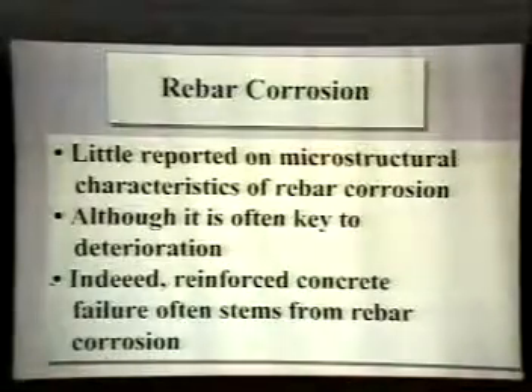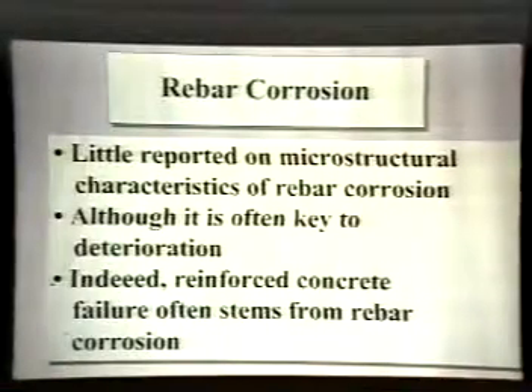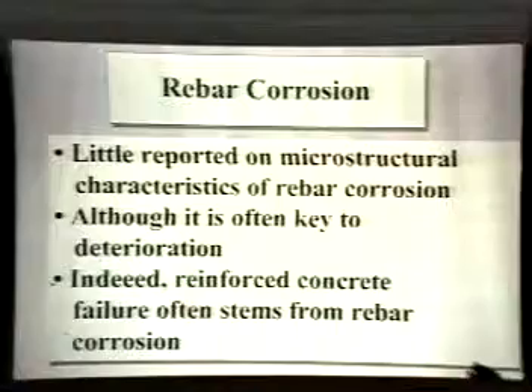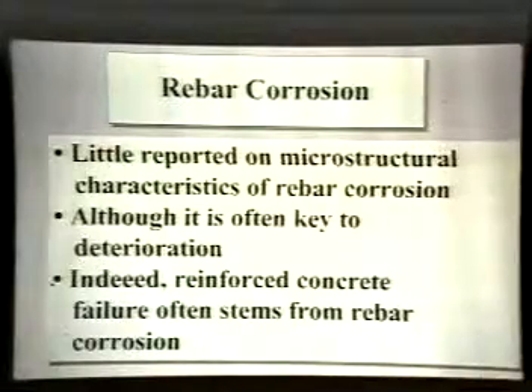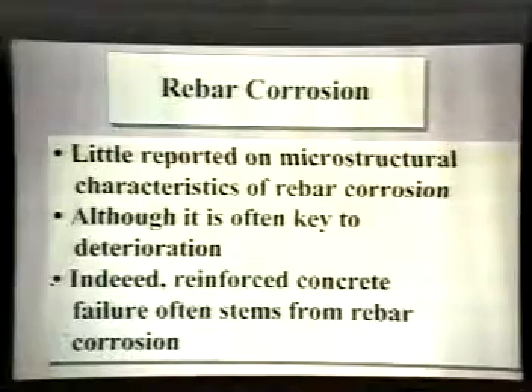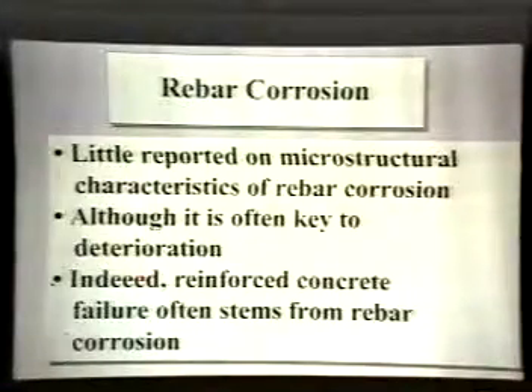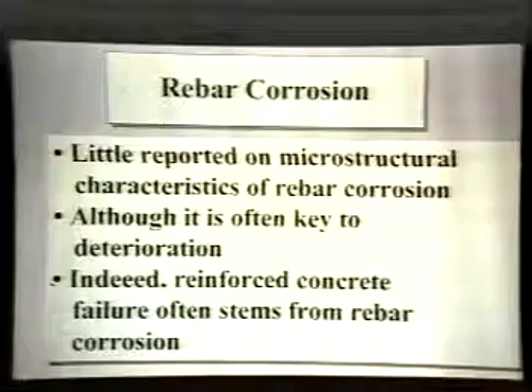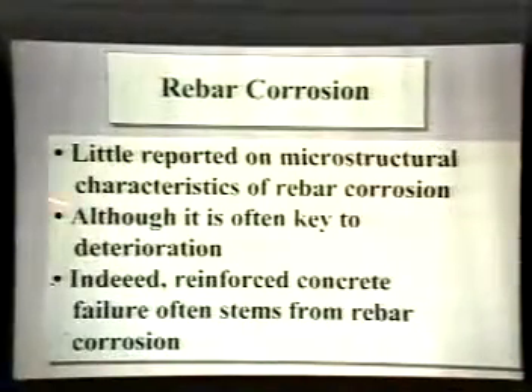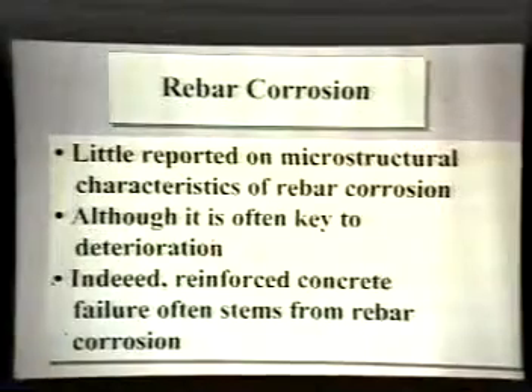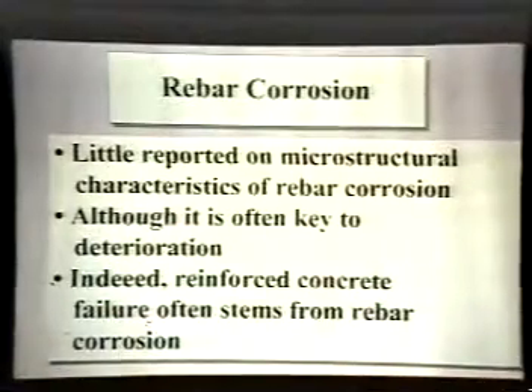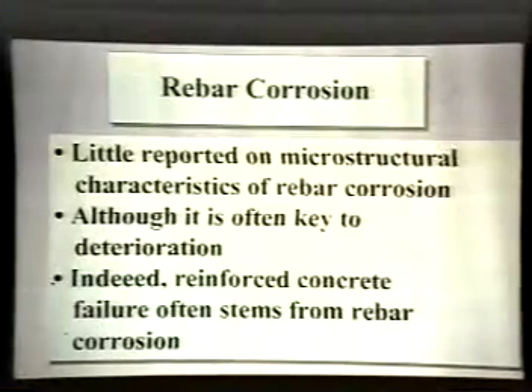So in this case, the problem was de-icing salt, but it had multiple effects in the sense that you had those expansive salt formations up to the rebar level, and you had a tremendous amount of rebar corrosion. Talking about rebar corrosion, very little is reported on the microstructural characteristics of rebar corrosion, although rebar corrosion is often the key to concrete deterioration. As a matter of fact, in reinforced concrete, failure often stems from corrosion of rebar.